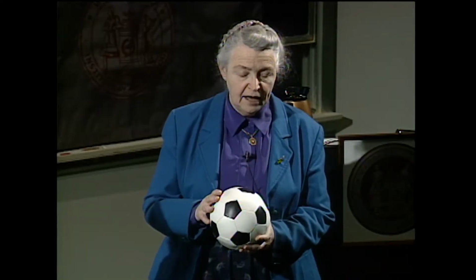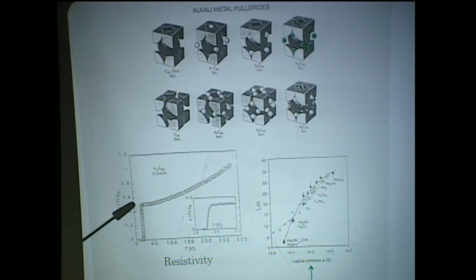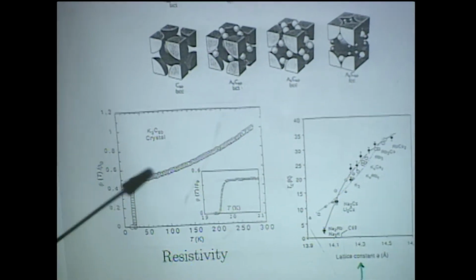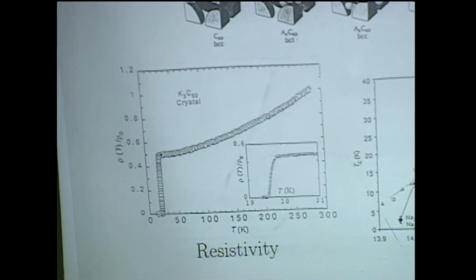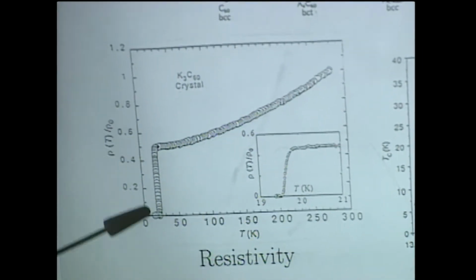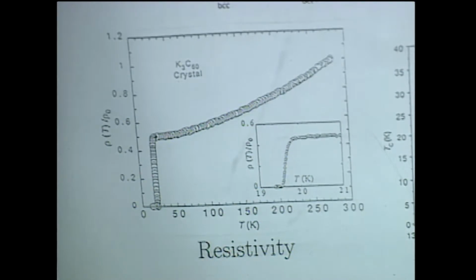A conduction band can hold six electrons. Three electrons half fills it. And that gives the maximum conductivity. So for that one, we, in fact, get metallic conductivity. So the resistivity goes up with temperature. That's a sign of metallic conduction. And when we go down to low temperatures, what happens is, voila, at some transition temperature, the resistivity goes to zero, and we get a superconductor. So not only do the buckyballs support metallic conduction, but they also support superconductivity.